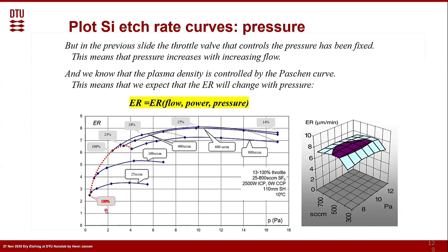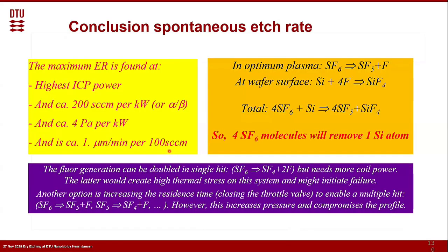And then we did the same by saying, okay, now we have a fixed flow and power, and we're going to change the pressure by changing the throttle valve of our turbo. So we are changing the residence time. And we find a new, even higher value. So it can be even 4 times faster. So it could be that we also come into the range where we create, even from a single SF6 molecule, even 4 radicals. And I will directly say why.